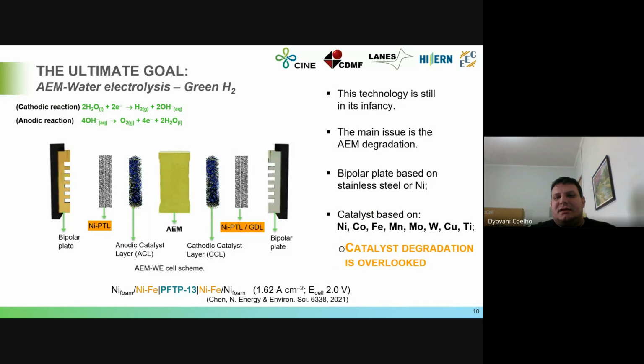But this kind of technology has a lot of advantages compared with PEM. The first one is the bipolar plate, which here can be just stainless steel or nickel, compared with titanium in PEM. And the catalyst can be made of non-noble metals based on nickel, cobalt, iron, manganese, and so on, because they are stable in alkaline medium and are active for this kind of reaction too. But the problem is that the catalyst degradation is overlooked.